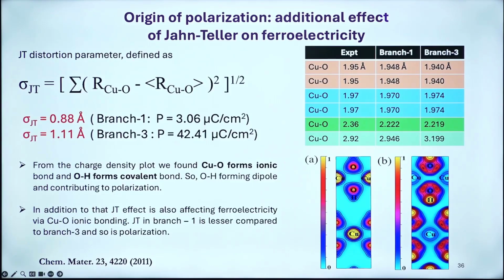And then, okay, so again copper is in the 2+ state. Okay, you always have the doubt, I know that. And it is a d9, na? And then this article in Chemistry of Materials, which appeared in 2011, also showed that the distance really matters between the copper and oxygen. We see that branch 1 has relatively 0.88, but branch 3, where the polarization is relatively large, has a larger value of 1.11. So we are trying to connect this. So this distance is also responsible.